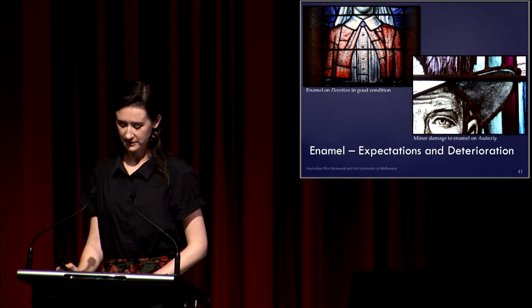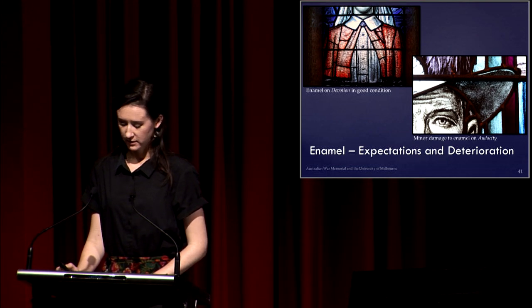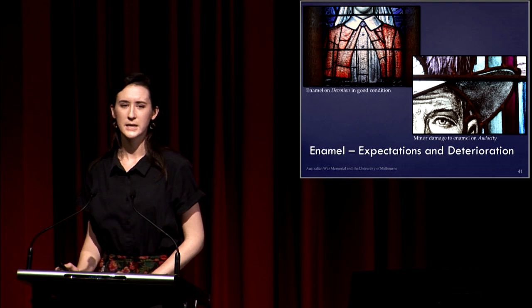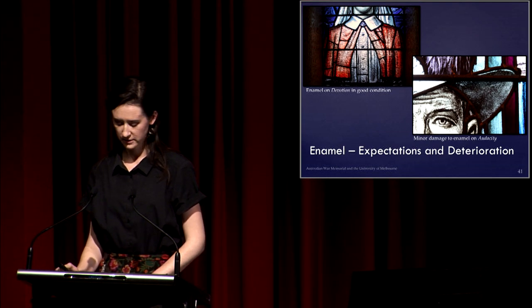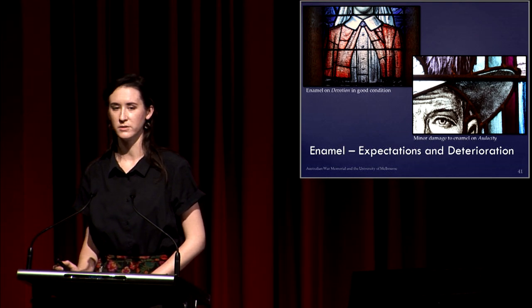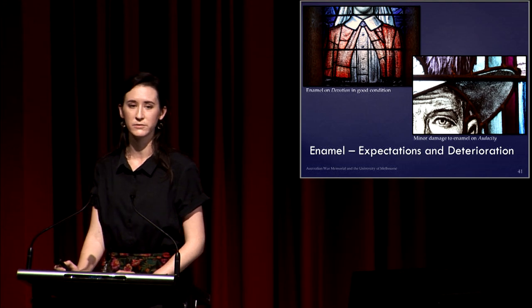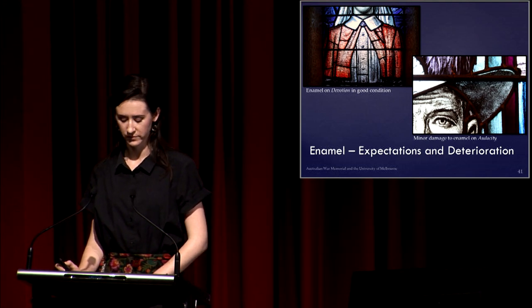We were also sadly finding several areas where the paint did not actually contain any silica, which indicates that it will have a very poor bond to the substrate and be more vulnerable to flaking and delamination in the future.